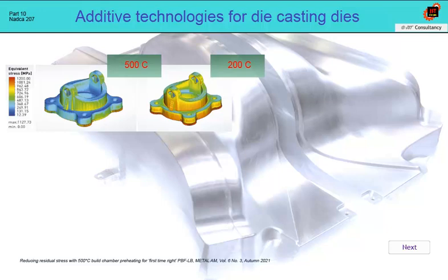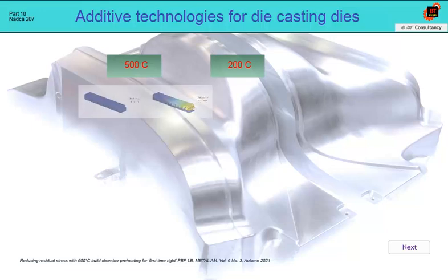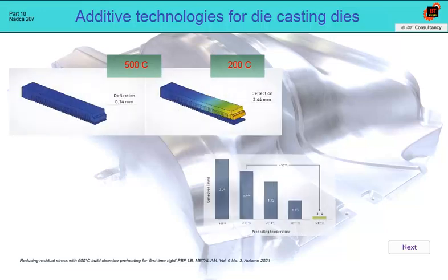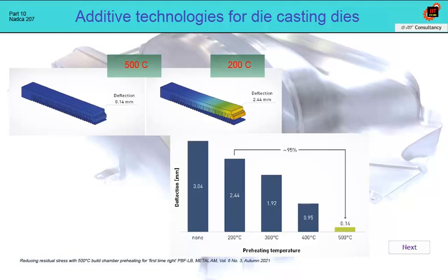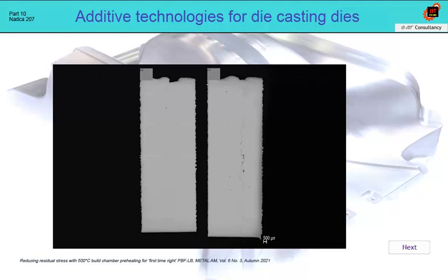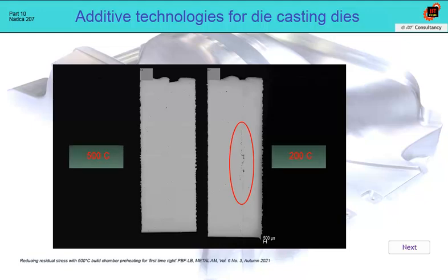On the left is the deflection of the sample on a substrate plate at a temperature of 500 Celsius, on the right at a temperature of 200. The result at a higher temperature is 95% better than when printed on a platform at a temperature of up to 200 Celsius. In the last picture, you can see the cracks inside the part made of H11 material, printed at a temperature of 200 degrees Celsius, image on the right, and the state after printing with a heated substrate plate at 500. The difference is quite obvious. The high temperature of the platform reduces the stress in the printed product, and thus also the tendency to form internal cracks.